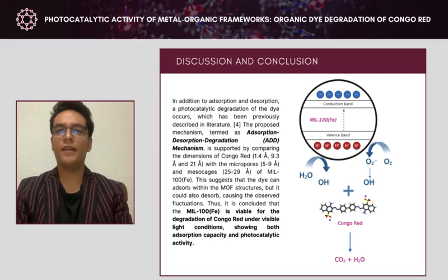MIL-100(Fe) is excited by visible light, and an electron-hole pair is formed on its surface. After energy absorption, the electron is excited from the valence band to the conduction band, leaving a free hole in the valence band. Electrons then reduce oxygen to oxygen radicals, which are then transformed to hydroxyl radicals. At the same time, holes oxidize water molecules to more hydroxyl radicals that decompose organic dyes effectively. Thus, it is concluded that MIL-100(Fe) is viable for the degradation of Congo Red under visible light conditions, showing both adsorption capacity and photocatalytic activity.